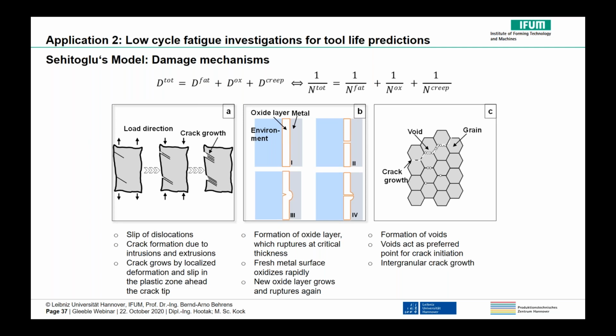These include crack nucleation and propagation due to the strain amplitude. The oxidation damage mechanism includes crack nucleation in surface oxides and oxide-induced crack growth. Creep damage is observed in the form of internal intergranular cracking at the grain boundaries.